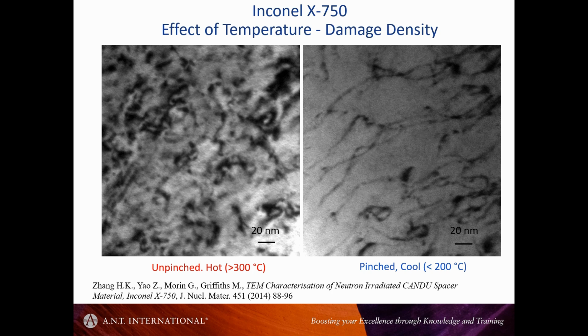In that example, I've just flipped through. I apologize, but I can't go back when I'm recording. In that example, and you can see it on the internet, very, very little radiation damage, but what little damage there was, albeit submicroscopic, was still sufficient to drastically slow down the dislocations, the dislocation slip. So having radiation damage is basically one way to harden the material, make it more difficult to get dislocation slip.